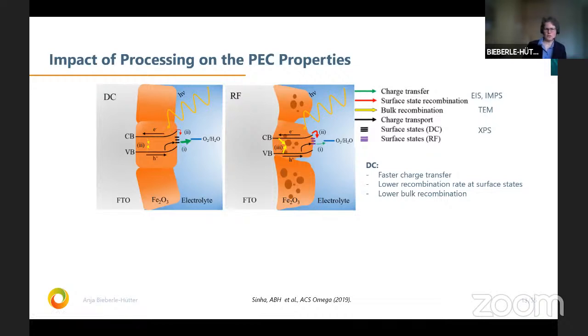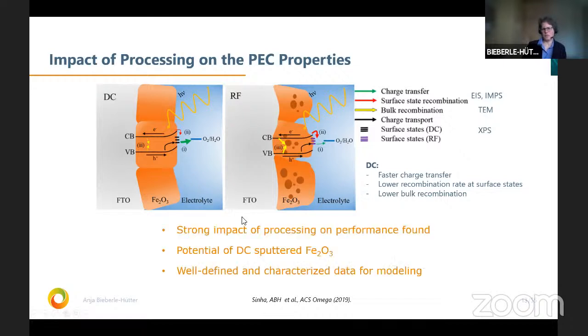So what do we learn now from this? We see a strong impact of the processing on the performance. A lot of people report this, but what is actually amazing with this study a bit is that the DC sputtering has actually the higher performance than the RF sputtering. And this is in this respect also pretty nice, because DC sputtering means that you sputter metallic iron, and afterward we anneal it, and we get a well-adhering, well-sticking oxide phase on top of our substrate. And this is actually, when you think application-wise, it's very nice, because this could be used for fast and easy processing. Yeah, this is the first thing that we learn of this.